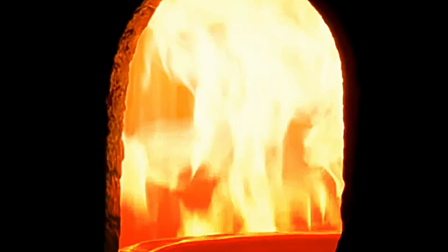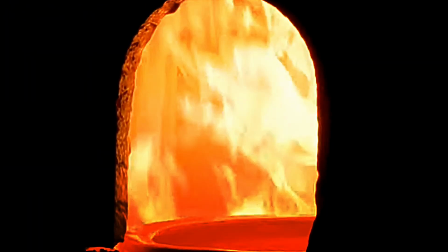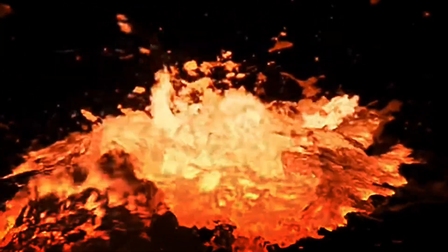Once the material is introduced, the opening is closed to preserve the temperature and maintain a stable atmosphere inside, ensuring uniform melting. During the process, long metal tools are used to stir the molten glass, releasing air bubbles formed during melting. Even small bubbles can reduce the glass's transparency and strength, so removing them is essential. Melting continues for 24 hours or more, enough time for all the components to integrate into a viscous, shiny mass. Only when it reaches the necessary homogeneity, viscosity and purity is the glass ready for the handling and forming stage.